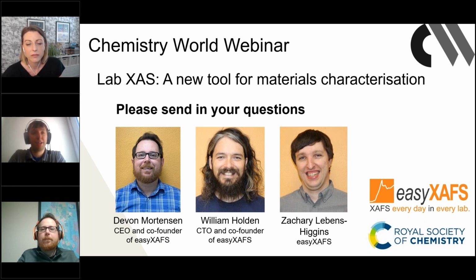Yeah. So for our instrument as well, you would have to do a calibration. It usually is done before a whole set of measurements starts or at the end, and it's usually a very short process, in order to reference to a metal sample. We have very high stability, so that metal reference can be used for all subsequent measurements on the same element. Then when you switch elements, you would do a new calibration. So rather than at a synchrotron where you're doing a calibration with every single sample, you're doing this one calibration, and then that will hold for all subsequent samples. Right, so that's done at the start of a run, and you only do that once? Yeah, basically when you're switching crystals or when you're switching elements, you'll do it once at the start of that element set.